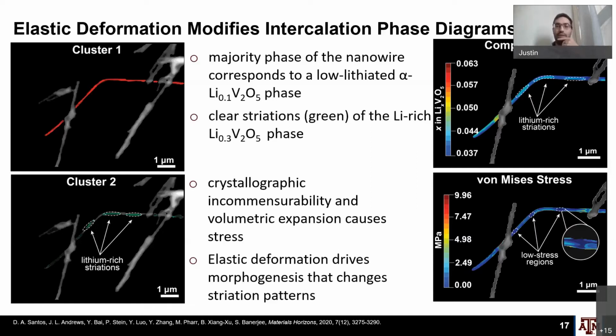Typically in a V2O5 nanowire, we see exclusively core-shell material, but in these bent nanowires, we see a lot of interesting striation patterns of localization. We've been able to do a lot of theory and modeling that shows this has everything to do with the way these materials are curved and bent.